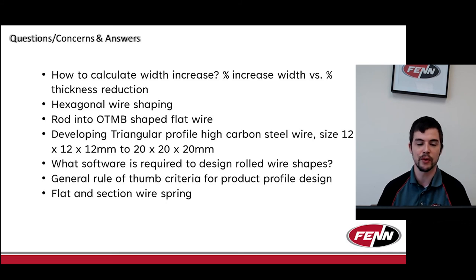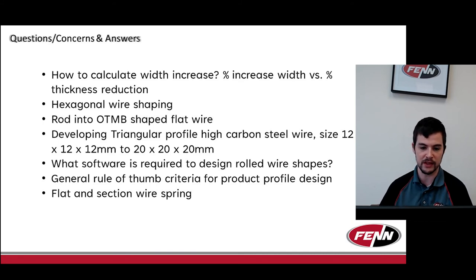The bigger your roll, the more it naturally wants to spread to the side, the more width you'll get versus a smaller roll. Same idea with thickness reduction. That initial hit, especially that first hit in a wire line, depending on the application, is the point at which you get your most spread.